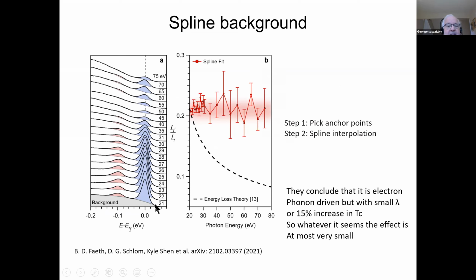But again, you have this large background that these things are sitting on. What they did is they used a kind of a spline method. So they just pinned the points in between the 2 peaks, the blue one and the red shaded one, pinned the background there and pinned it on the other side over here and a few other places, and did that all the way through. Now, the problem with that is that there is another peak in between here.